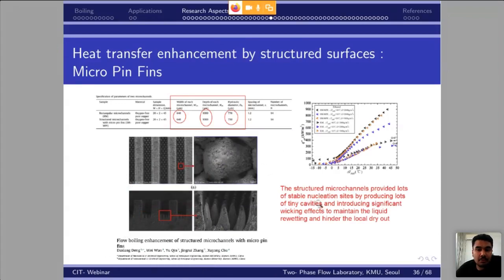These tiny cavities can produce a lot of nucleation sites, and they can also wick a lot of water towards the surface, and that can enhance the boiling and increase the critical heat flux values. Okay, the main thing is the more stable nucleation sites and also that wicking effect that will increase the CHF. This curve shows the proof, without microstructures and with microstructures. With microstructures, they can attain a higher CHF value.